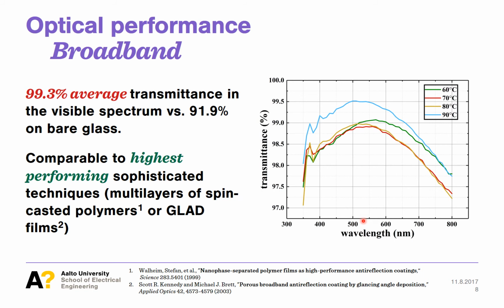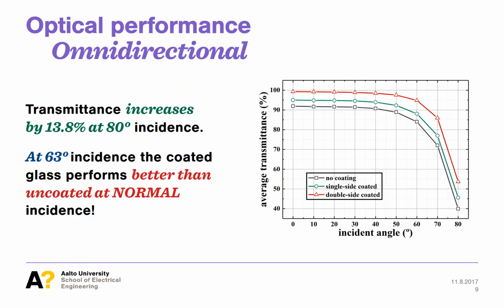Grass-like alumina outperforms most published anti-reflective coatings on glass. It has performance comparable to the best multi-layered glancing angle deposited films or multi-layered spin-casted polymers. Simplicity of fabrication and massive scalability with this kind of broadband transmittance are unprecedented. Additional experiments have confirmed that it is possible to tune the peak transmittance to the near ultraviolet range for grass-like alumina deposited on quartz. Our coating also has impressive omnidirectional performance.